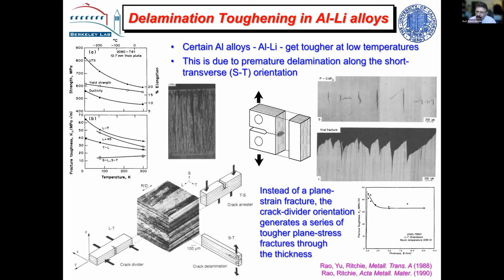Now they're FCC, right? They're face-centered cubic. We don't expect a ductile-brittle transition, but most alloys, even things like aluminum alloys, this is a plot here of the toughness versus the temperature. They sort of stay relatively flat. But this particular alloy, and these are the aluminum-lithium alloys particularly, actually get tougher at lower temperatures. They get stronger, of course, but they get tougher as well.